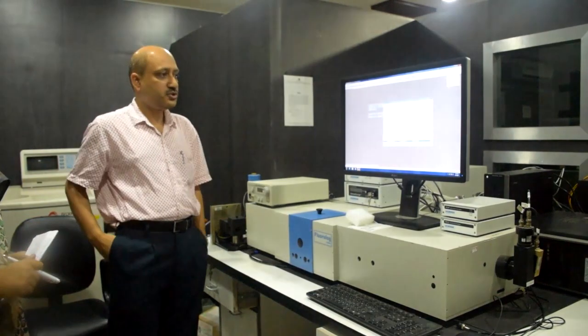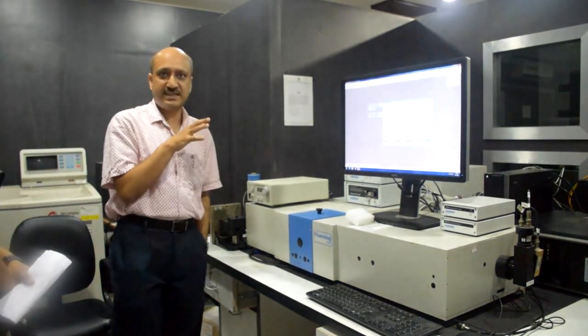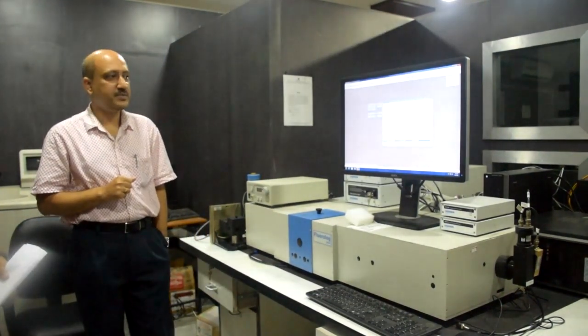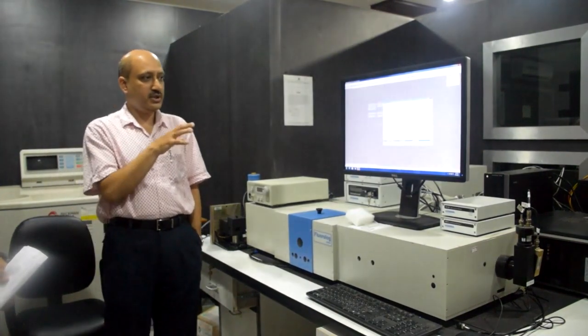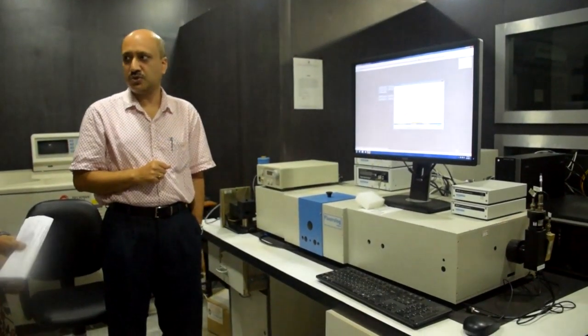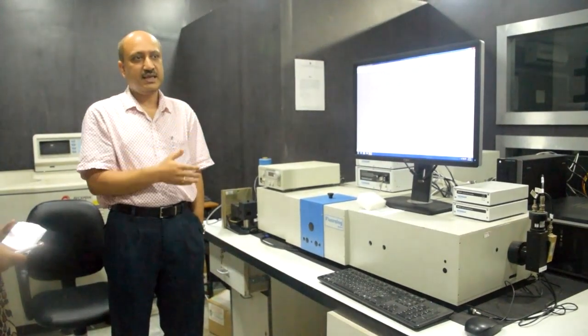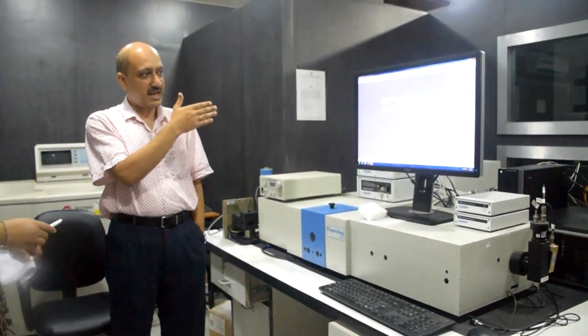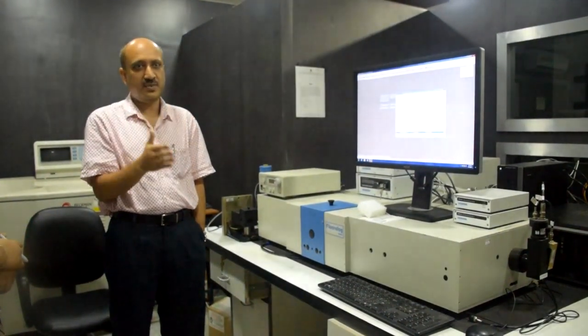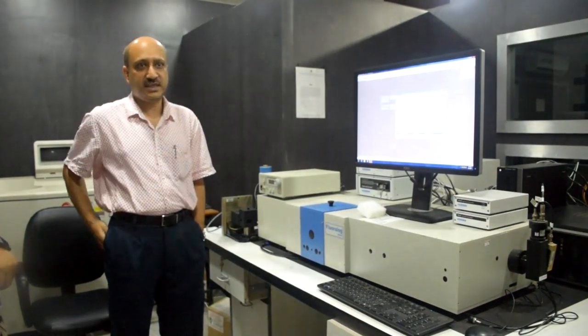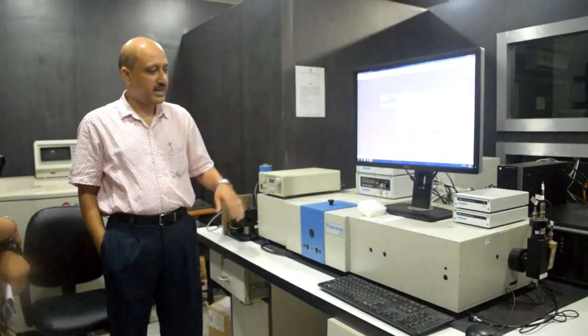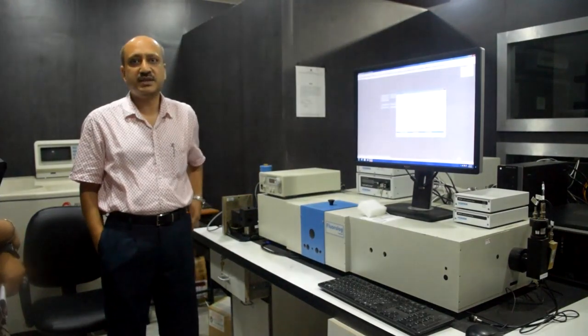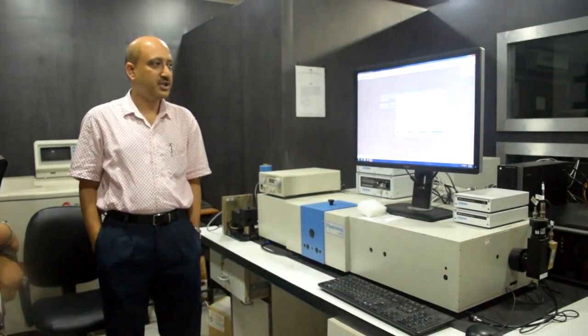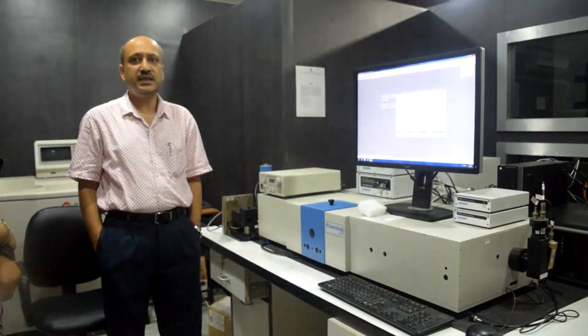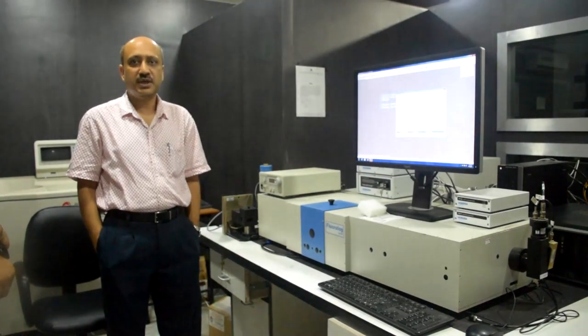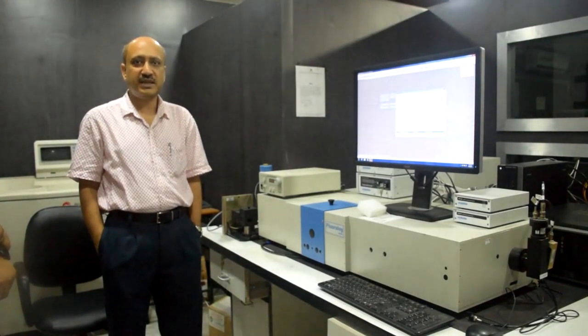And we are equipped with not only the steady state excitation and emission spectroscopy, we are also equipped with a pulsed excitation source, which basically implies that we can avail a delay time and a gate time to collect the longer lifetime decay profiles. And also we have another setup which is called time correlated single photon counting. Based on that, one can determine the lifetime of the fluorophores in the picosecond to nanosecond time scale as well.